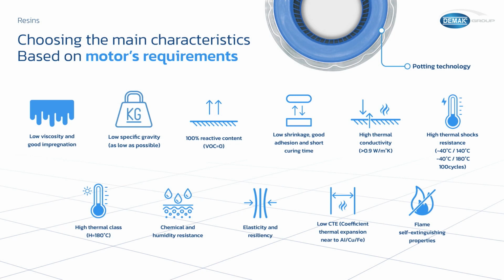In the meantime, high thermal shock resistance, because it's very important when we have a quick passage from cold to warm condition to not have cracking. It is a parameter that is related a lot to a low coefficient of thermal expansion. That must be the lowest possible, because the resin must be near the coefficient of expansion of the metal of the winding. Flame retardancy is also important for the safety of the car.